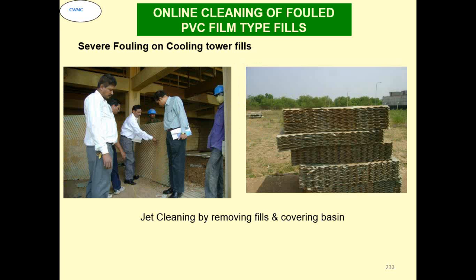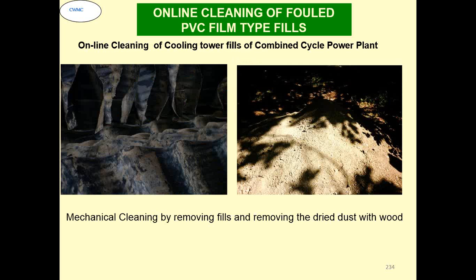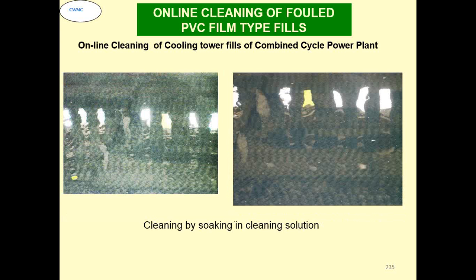This is the kind of fill packs that you see. They are removed and mechanically cleaned. Normally in the mechanical method, people allow the fill packs to dry out, and then with some wooden piece they beat it, so all the dirt goes out. But in that process, the fill packs also get damaged because they are made of PVC. They become brittle and break, and after some time you have to replace the fill packs. So this is what was happening.